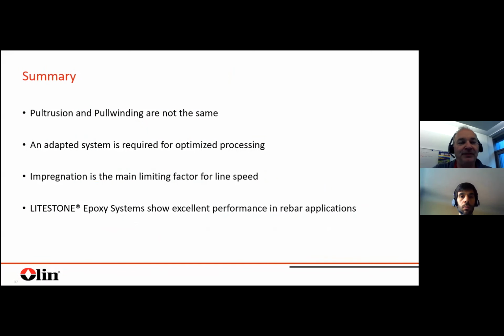So my summary: first, pultrusion and pullwinding are not the same. As I tried to explain the reasons for it, to optimize for your process and productivity, you should carefully look at an adapted system and maybe also find a good way to adapt and coordinate the resin characteristic in your process setting. From my point of view, the impregnation is also the main limiting factor, as explained, due to the impregnation itself and the requirement on pot life. And we have systems in our LITESTONE portfolio, as mentioned, which show an excellent performance, which are also qualified against different standards, especially in the rebar specifications.